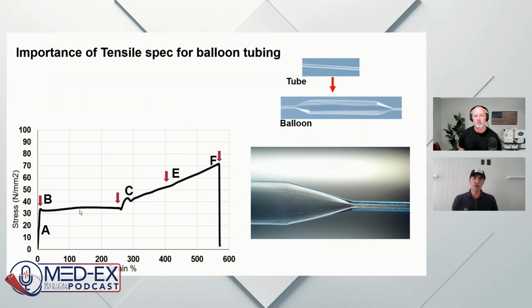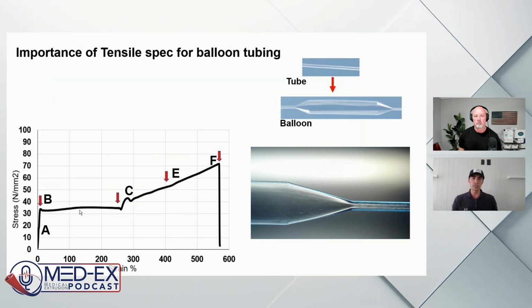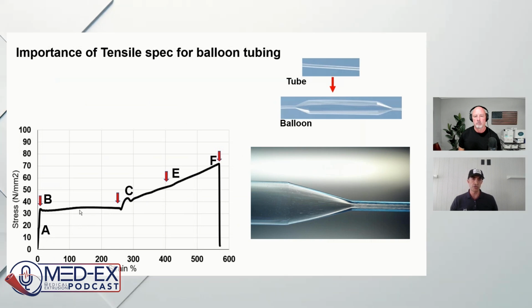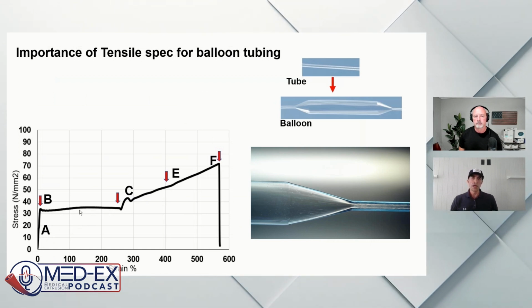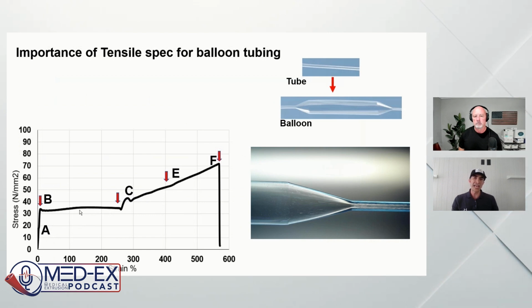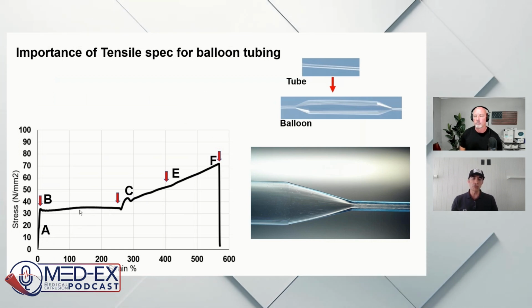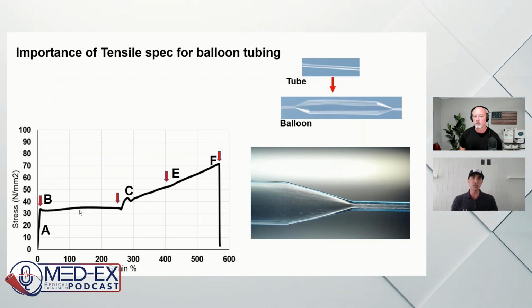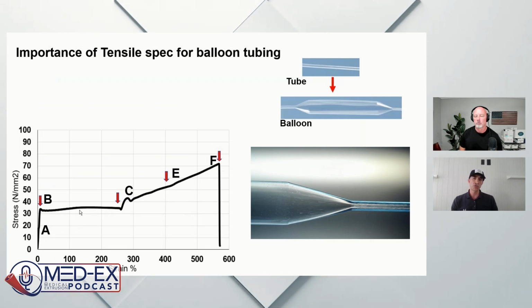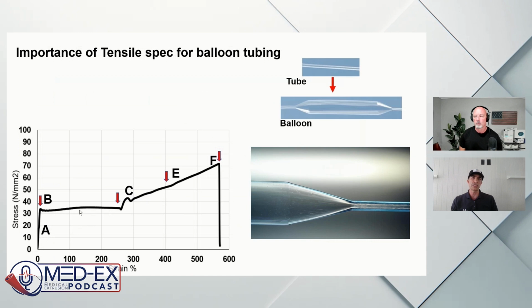right? For a nylon 12 specifically, the yield point and the elastic modulus are not very important for balloon forming, because we are already in the formation zone, right? So we are basically past point C, right? Yeah. So specifying probably two points on that region between C and F would be a good starting point, right? Like a strain at break and some point closer to C that will show, okay, now your material started to transition from necking down to strain hardening. That will be a good point also to be specified as a tensile spec.